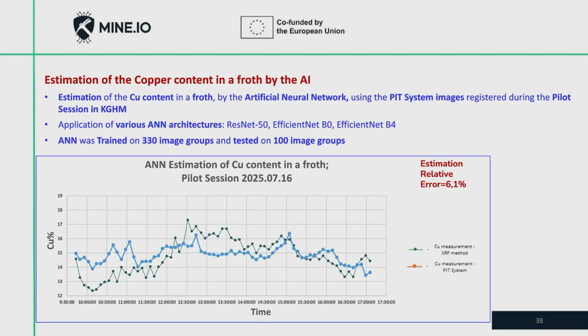Okay, perfect, thank you. So the estimation of the copper content in the froth is done by the AI. During the pilot sessions, during the MINE.io project implementation, we generated groups of training images that were associated with the copper content that was tested in the laboratory. Then we took other image groups that were not associated, and we checked how different artificial neural networks estimate the copper content. Based on that, we selected the best one, which achieved an average relative estimation error of about 6% compared to the traditional methods used in the processing plant, based on XRF.